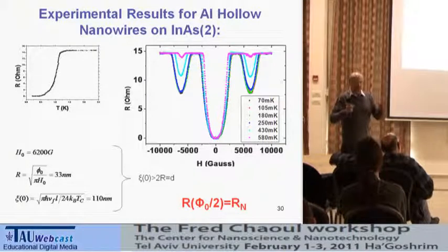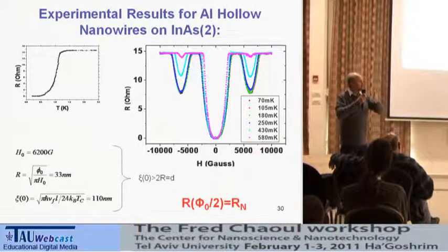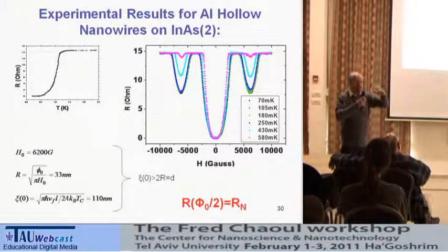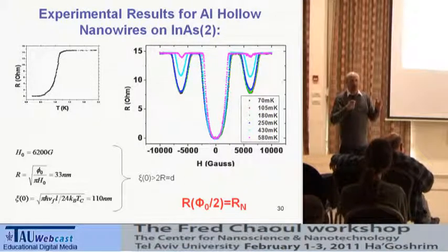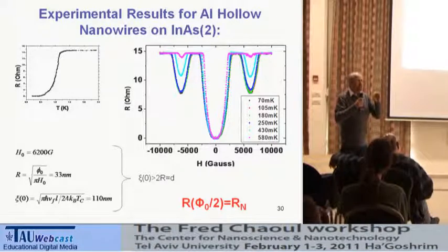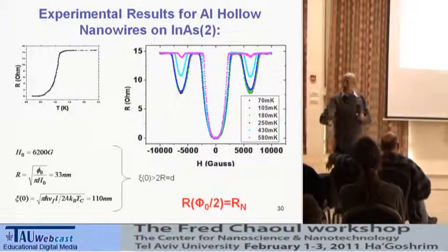There is a big debate now starting about additional systems, like a two-dimensional system that was also found, which should also be insulating. Insulating means that in principle they should show some increase in the resistance when the temperature is reduced, some kind of what we call Anderson localization. So all two-dimensional and one-dimensional materials should eventually, if they have a slight amount of disorder, go to infinity. And this system shows that it's not. This is really very interesting and new. That's my comment to the students who were participating in the course.